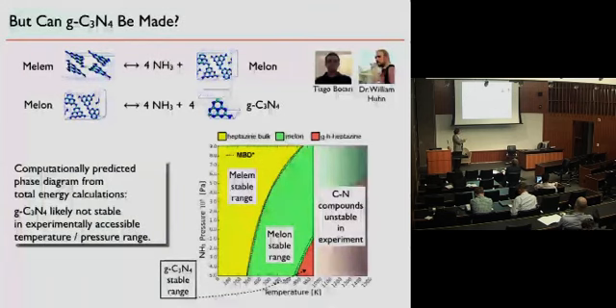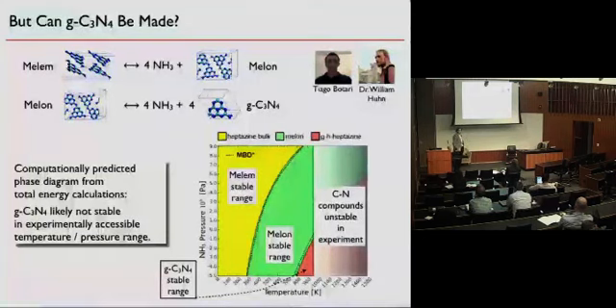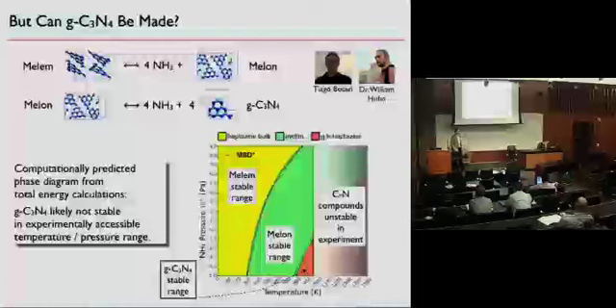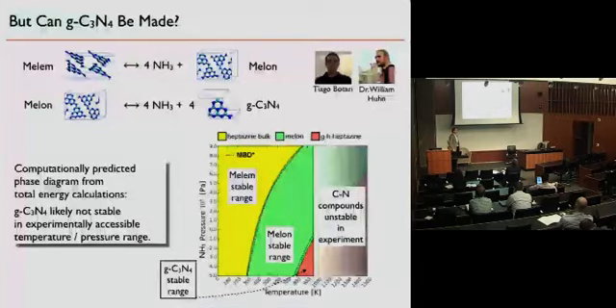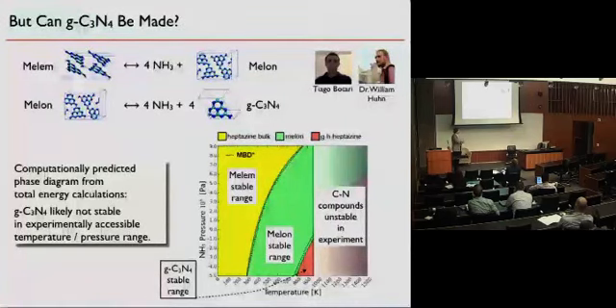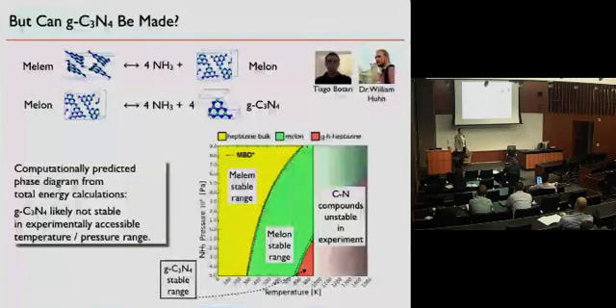So this is a logarithmic scale. This is about 10 to the minus 8, 10 to the minus 9 below atmospheric pressure for ammonia. And then at very high temperatures, almost where these compounds become unstable as a whole in an experiment. So if you have a framework that gives you such a prediction, you can see relatively easily that perhaps a straightforward chemical synthesis route, which has been tried for 15 years or so for that layered material here, is not the way to go. It's actually relatively unlikely that this is the route to make it, and that, of course, also creates opportunities to make it later.